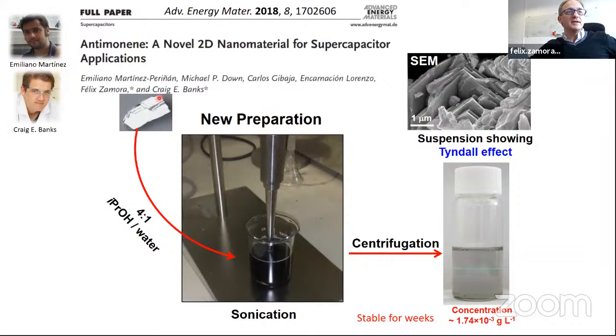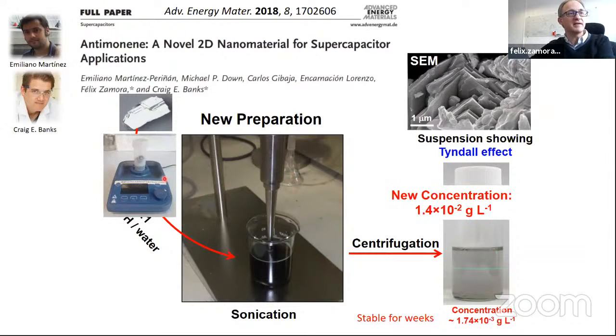For that, we used the liquid phase exfoliated antimony that we prepared, as I told you before, following this route. But in order to enhance the concentration of the final suspension, we introduced a new step. Before sonicating the samples in water isopropanol, we introduced a kind of wet ball milling, using water isopropanol as protective solvents in order to reduce the size of the initial crystal. So it's a previous process that we implement before sonication. And the final result was that we enhanced the final concentration by a factor of 10.